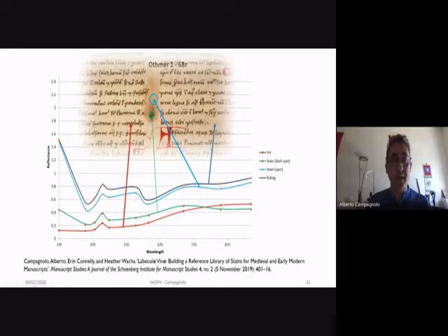You get the spillage of the ink for the text, and the blemish that's around it is a spillage of the ink that was used to do the ruling of the manuscript. So this all happened at the same time as the manuscript was written, and the plotting of the reaction to the lights of different materials allows us to identify the materials without having to do any other kind of destructive analysis on the object. So, which is quite cool.